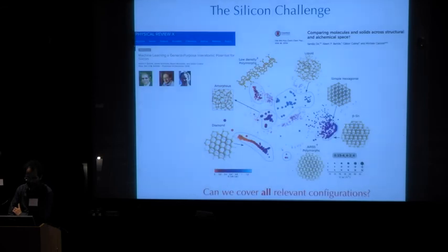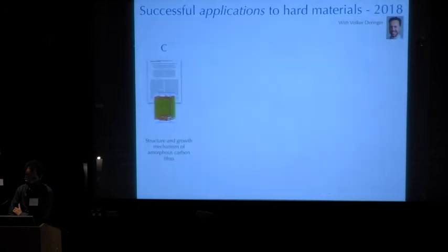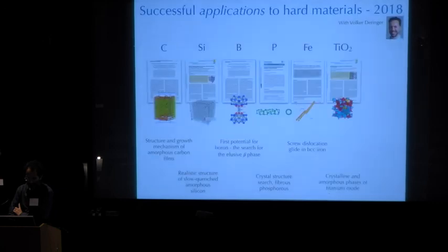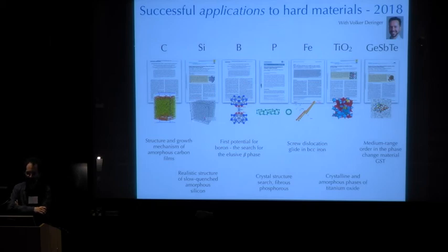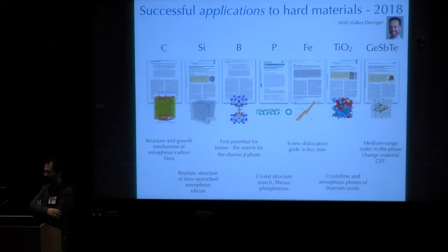And that's right. And actually, a lot of these models are of a similar class. They're all amorphous. And I said we need protocols. I don't have universal ones, but we're very interested in working on that. So we have protocols to say, what do you need to do if you want to model an amorphous system? We run a quench from high temperature. We start with random atoms. We place the atoms randomly. We train a crude model.